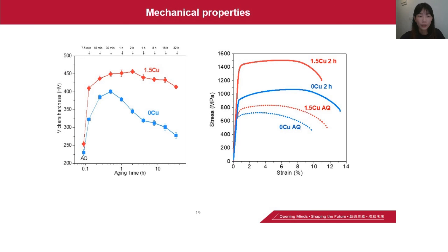Furthermore, we checked the mechanical properties. The Vickers hardness and the tensile test were performed to investigate the copper effects on the mechanical properties. As we can see from these two figures, the continuous precipitation in copper-modified steel shows a higher hardening response and over-aging resistance, and the yield strength was improved by copper addition from 900 megapascal to 1,400 megapascal. And the ductility was not sacrificed with increased yield strength.